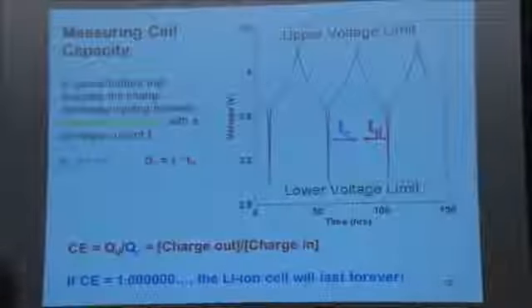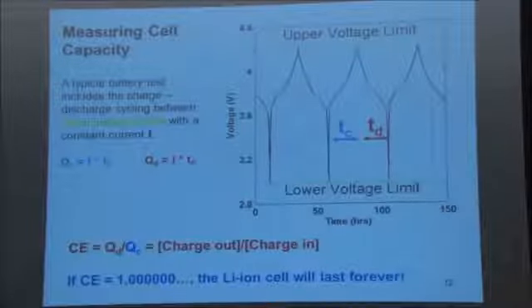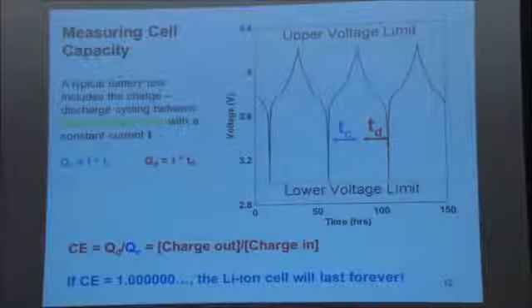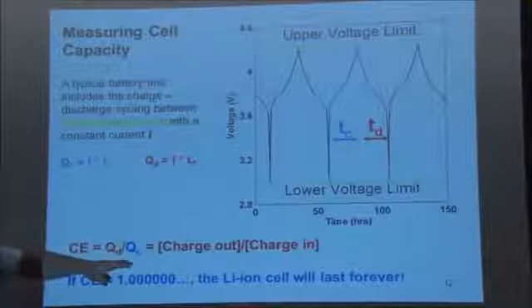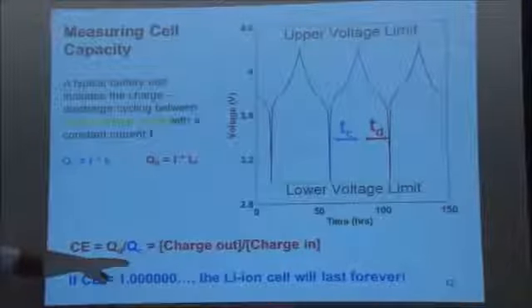But the point is, because of the parasitic reactions between the electrode materials and the electrolyte, this Coulombic efficiency is not exactly 1. And if you could measure the Coulombic efficiency really accurately, you could use it to tell the magnitude of the parasitic reactions going on in the cell. And that's going to be the point of this lecture: what can you learn about cell lifetime if you measure the Coulombic efficiency really accurately.